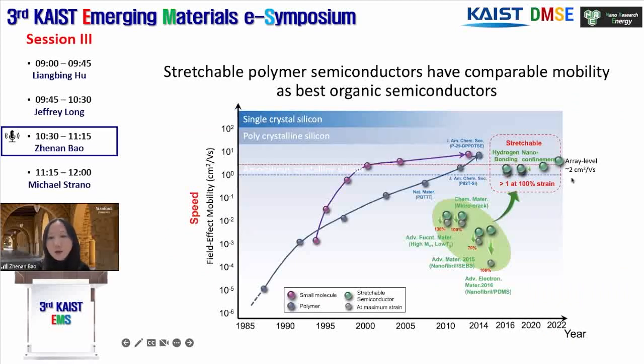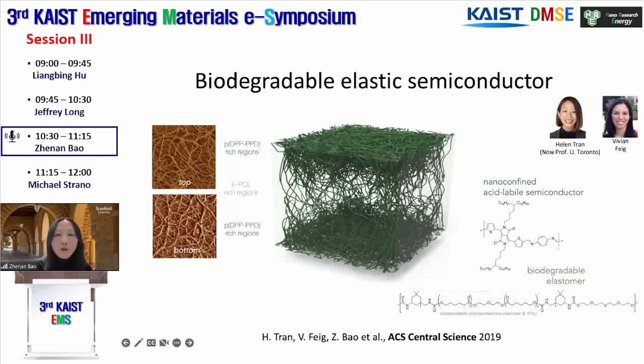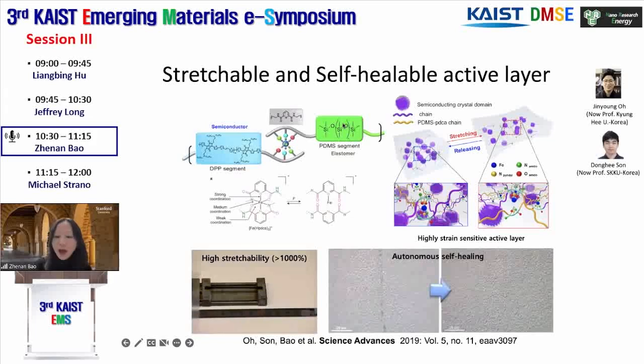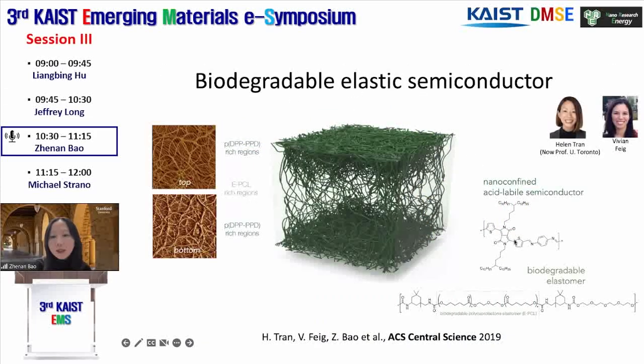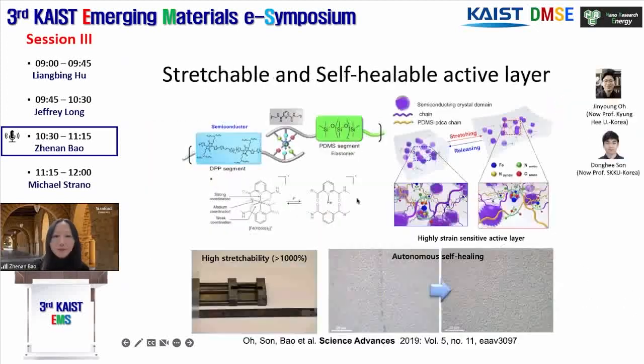So with these various molecular design approaches, and especially the nano-confinement, we're able to significantly boost the charge transport of organic semiconductors to beyond that of the amorphous silicon level and entering into the polysilicon regime. And we are very excited about this discovery of the nano-confinement effect because it's key for us to add other skin-like properties without degrading the electronic property, and even enhancing it. For example, adding biodegradability and elasticity can be achieved by using a matrix that's biodegradable and elastic and a semiconductor that contains an imine bond that can be readily hydrolyzed instead of a carbon-carbon double bond.